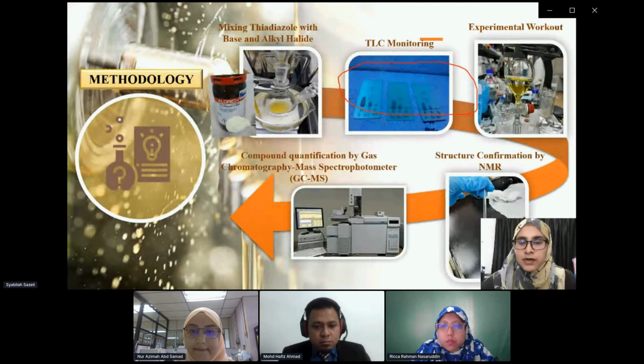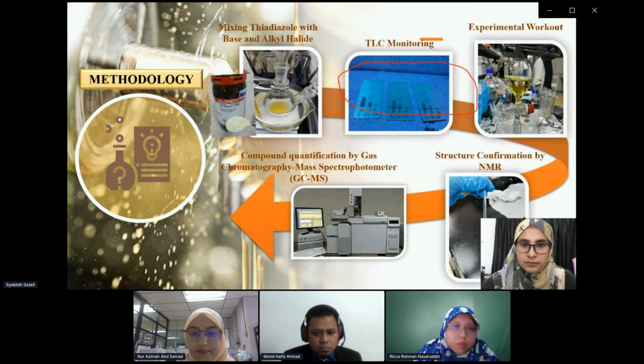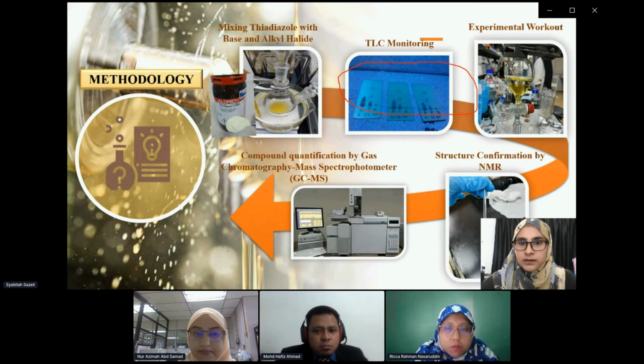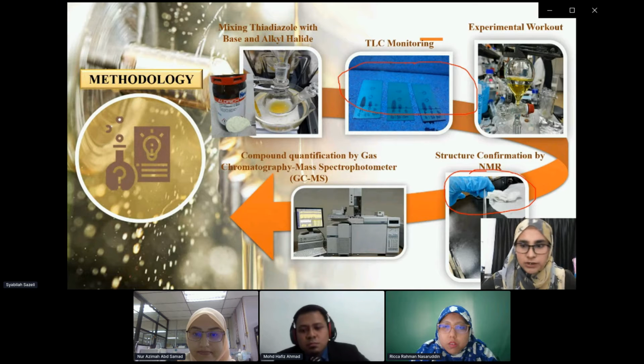Then we go for experimental workup to remove the solvent and unreacted material before purifying the product. After we separate the product, we send the sample to NMR for structure confirmation. And lastly, for further analysis, we send the sample to GCMS for compound quantification.